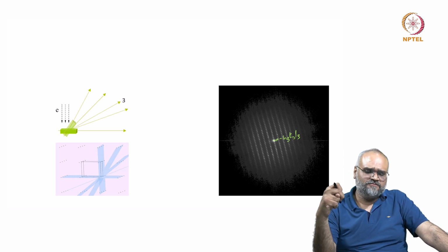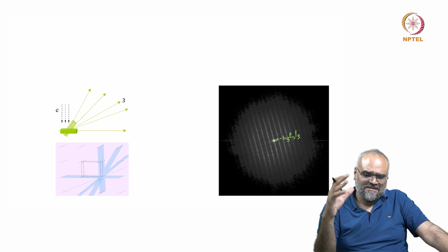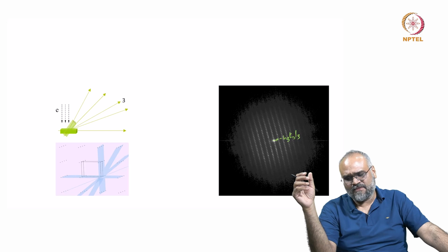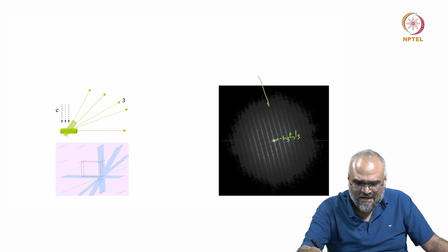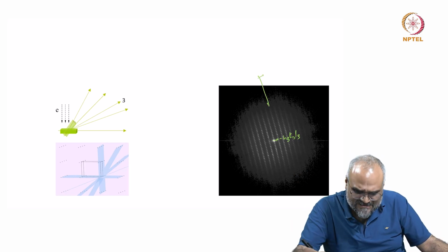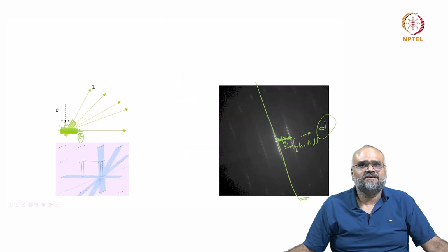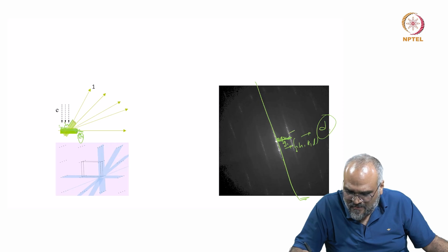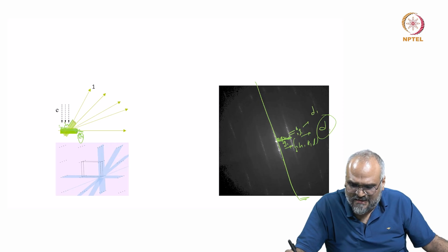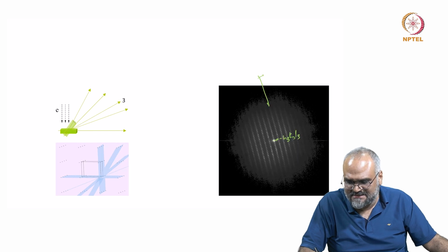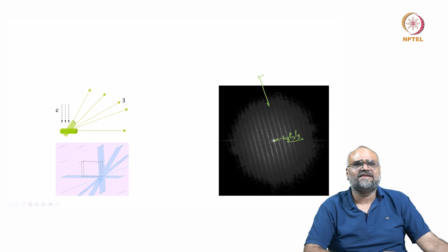So, essentially if I look at the diffraction patterns now as two-dimensional distribution of intensity and spot patterns which are coming from planes of crystal satisfying for three different lattice spacings, by maintaining one particular direction constant, or in these three cases if I fix this particular distance as G1 and in real space if I call it as D1 corresponding to H1, K1, L1, here I have this G2 changing and then this G3 again some other H3, K3, L3.